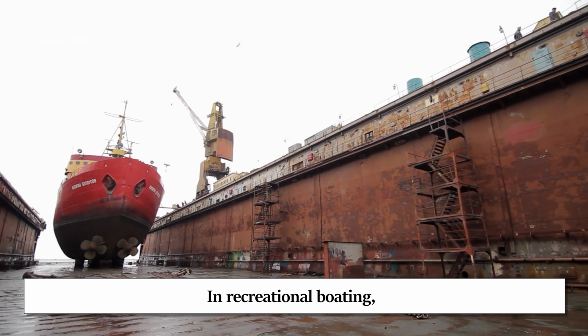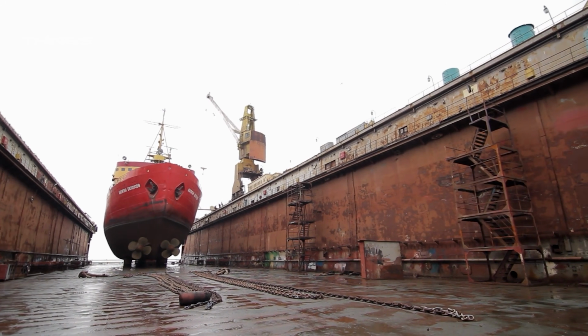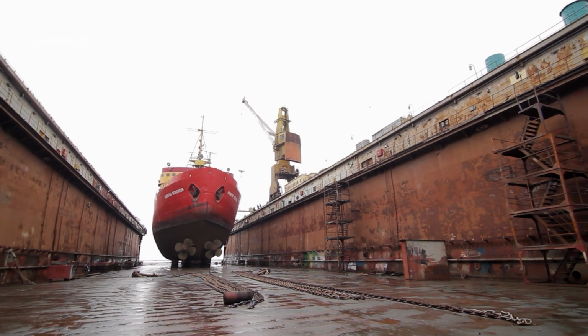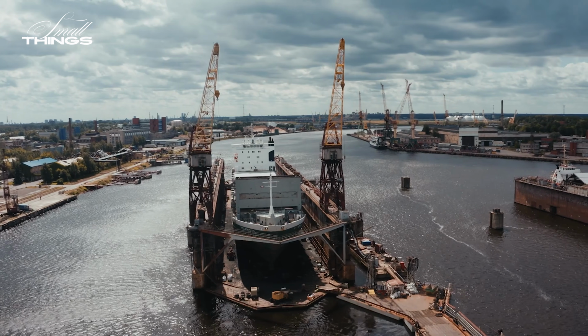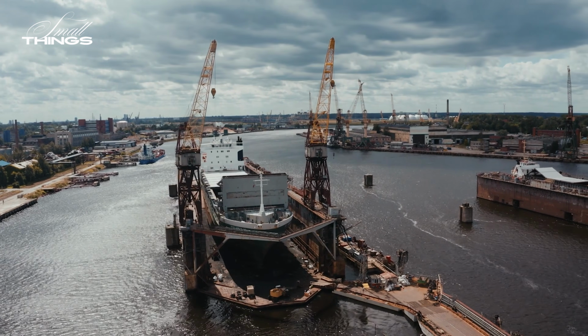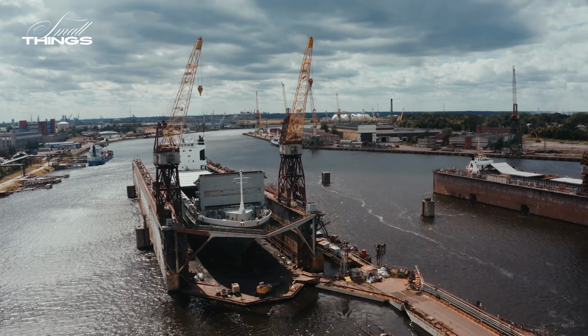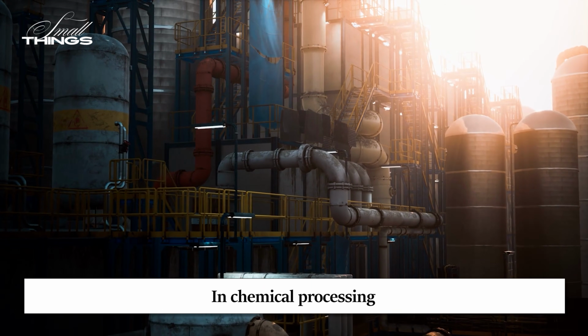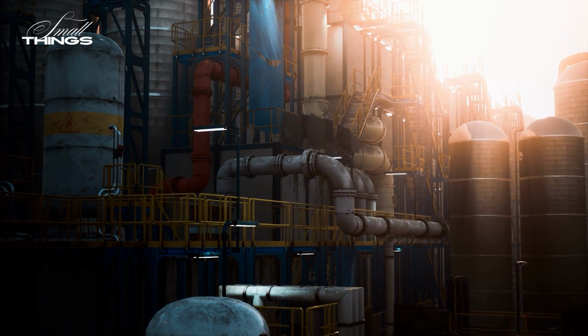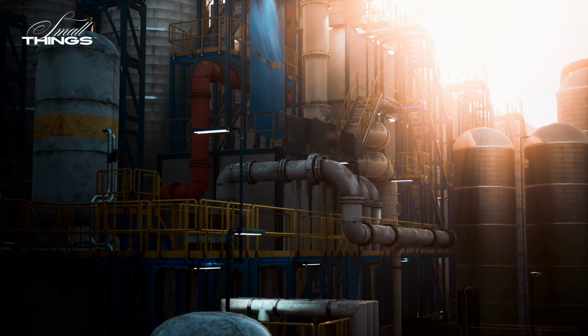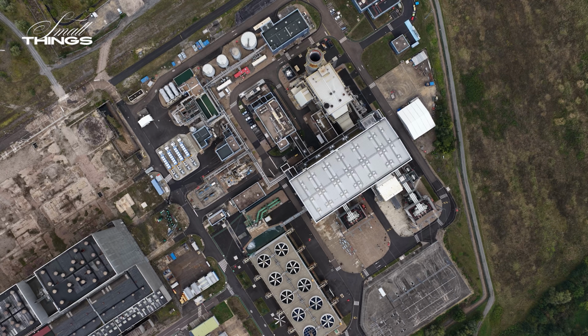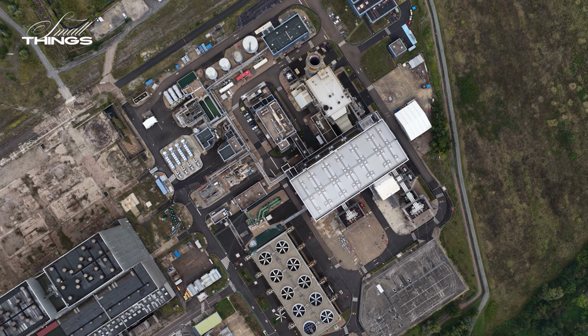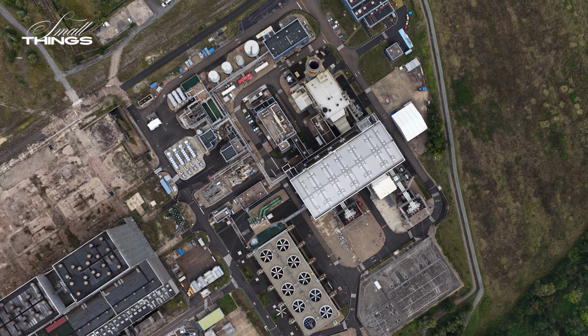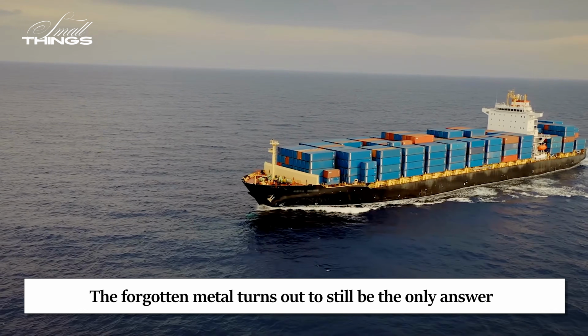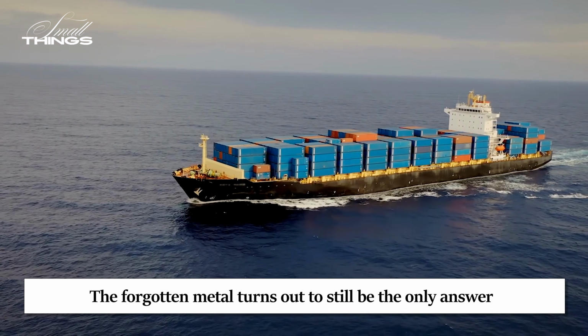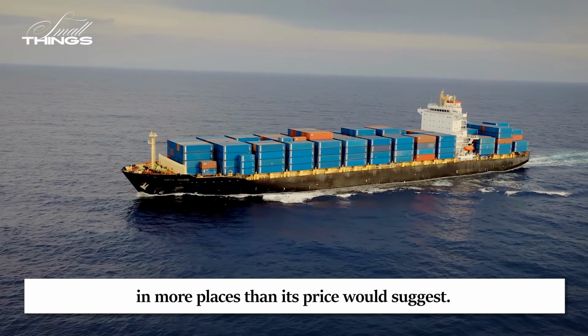In recreational boating, Monel rivets are still used on certain aluminium-framed boats precisely because stainless steel rivets in contact with aluminium in seawater would drive galvanic corrosion through the frame. In chemical processing, Monel handles hydrofluoric acid in conditions where most other metals would be consumed within months. There is no obvious substitute that does this reliably at comparable cost over a comparable service life. The forgotten metal turns out to still be the only answer in more places than its price would suggest.